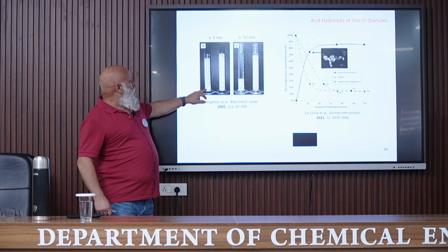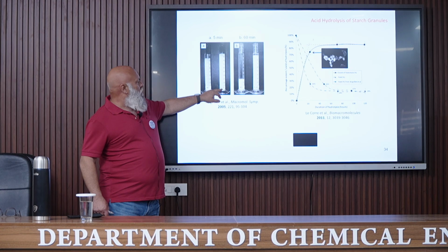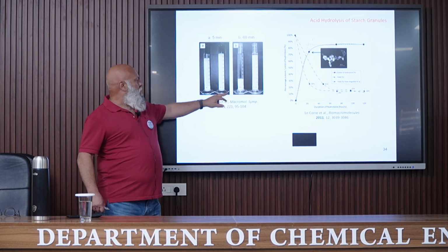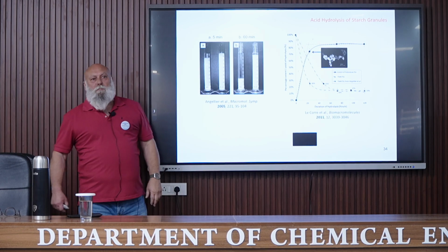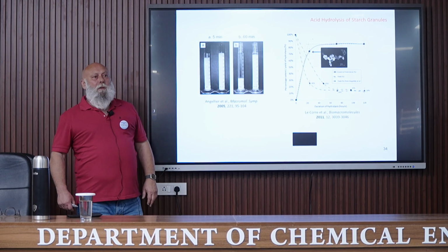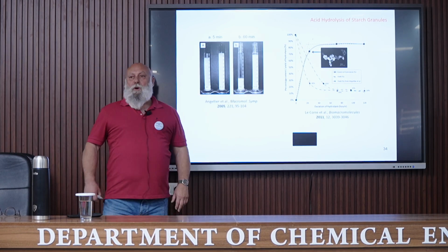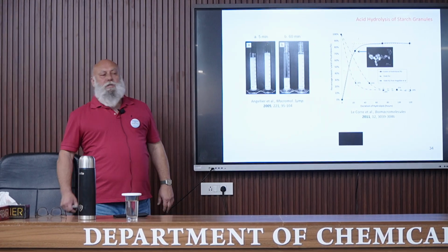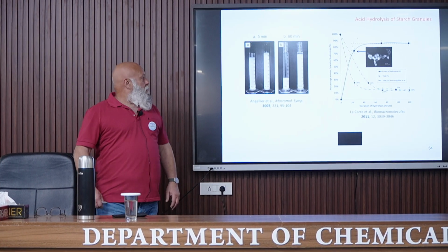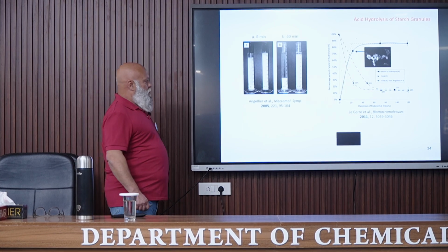So we can just see here the stability of the suspension. After 5 minutes or 60 minutes stirring, when using hydrochloric acid or sulfuric acid, as I told you previously, when using hydrochloric acid, the suspension is not stable. But when using sulfuric acid, because of the sulfate groups which are introduced at the surface, the stability of the suspension is much better.